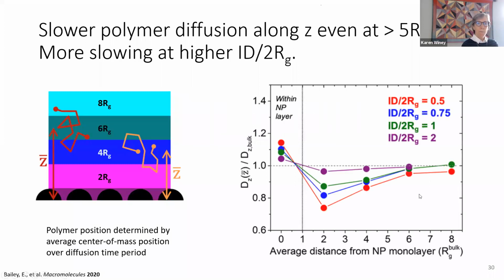Okay. So we see that far away from the nanoparticles, it's just about normal. So this is, again, the diffusion coefficient in the Z direction relative to the diffusion coefficient in the Z direction in the bulk. So very far away, it's just about what you'd expect for the bulk. And as you go towards the monolayer, the diffusion gets slower. And it gets more depressed. There's a more significant change when the particles are very close together, right? When we're in a very tight packing. And then once you're inside the layer, things move a little faster than they do in bulk.